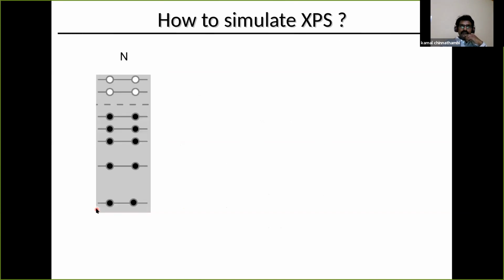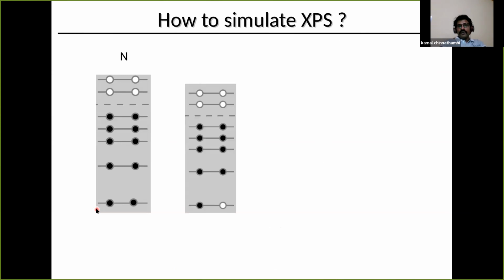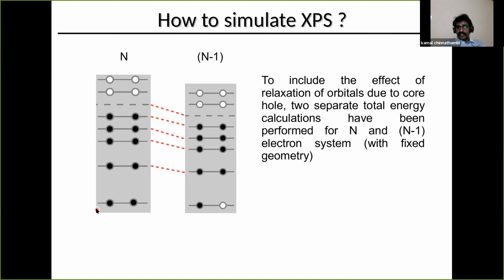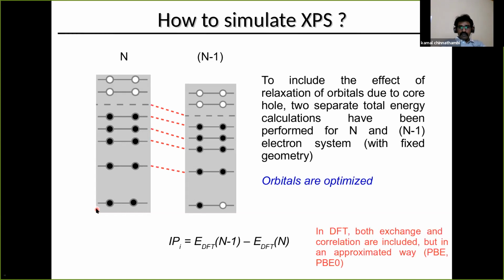In DFT, instead of using the orbitals to calculate the energy, we perform two separate calculations. One is with n electrons, another is with n-1 electrons. You can see that these two represent the initial and the final state. Also, the energy levels can be relaxed because in both cases we completely optimize the orbitals, so the relaxation effect of the core hole is intrinsically taken care of in the second calculation. So we simply take the energy difference between the n and n-1 systems. That gives you the ionization potential, which is equivalent to the binding energy.